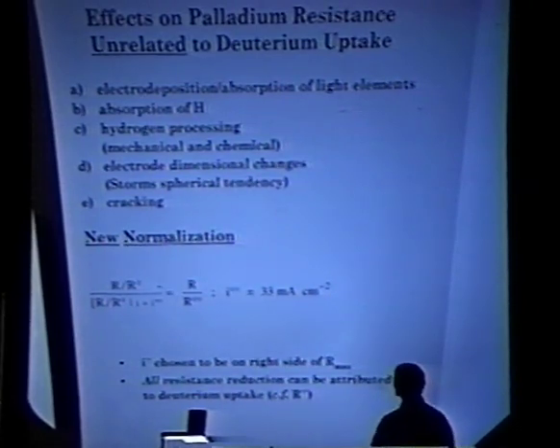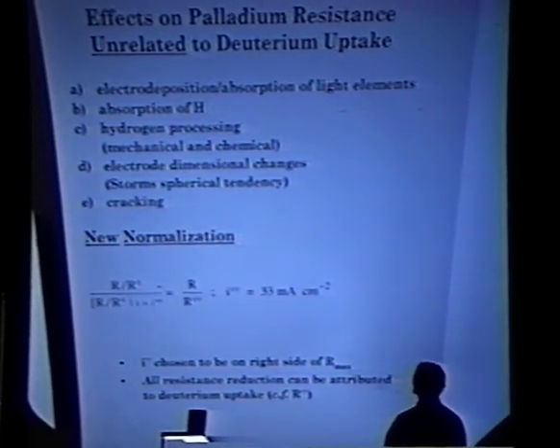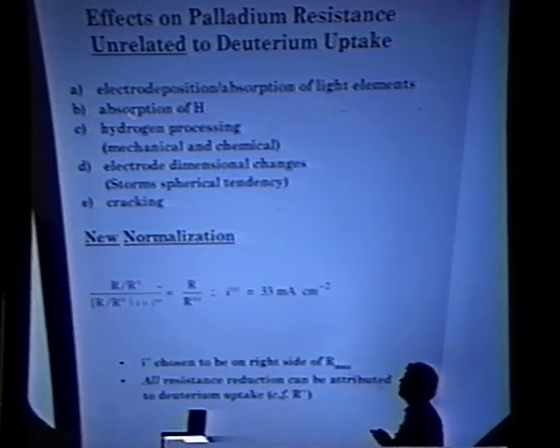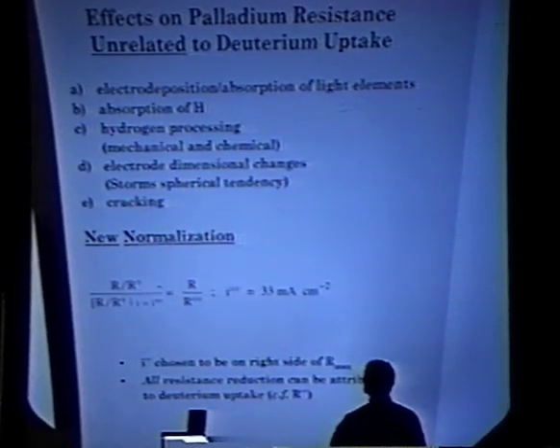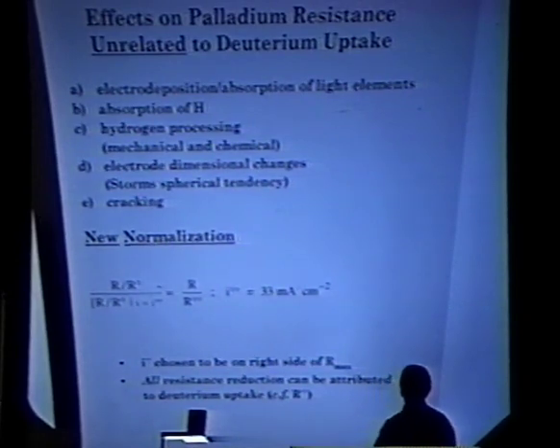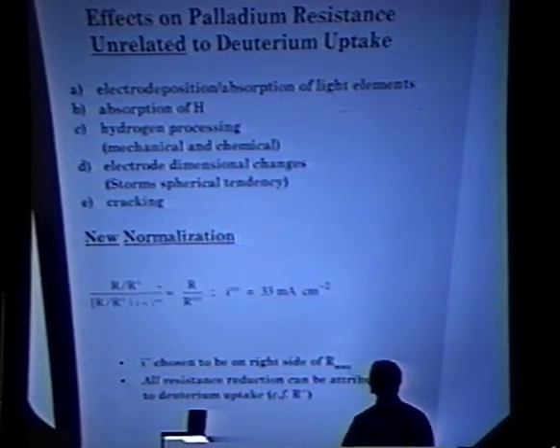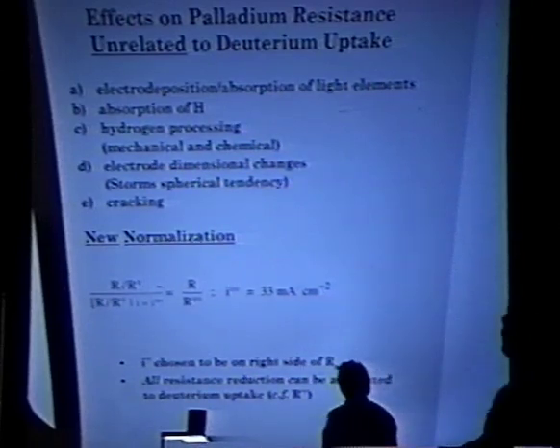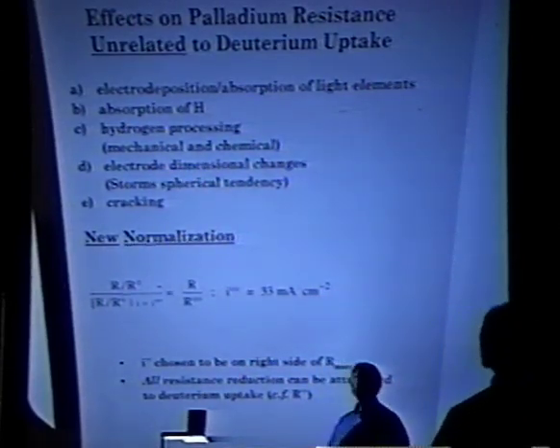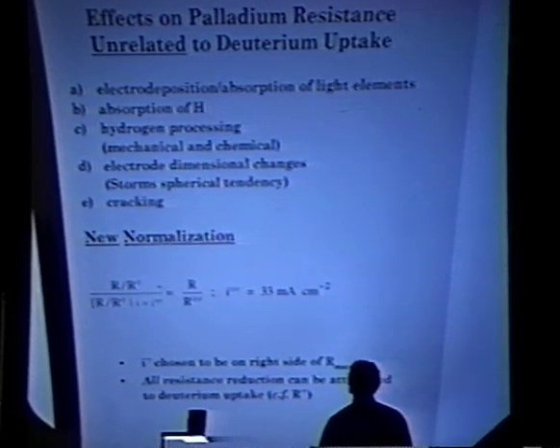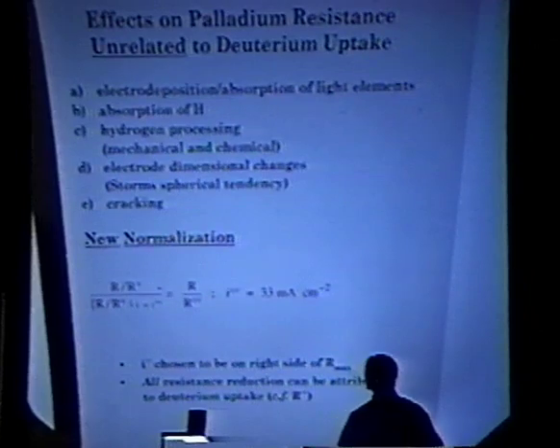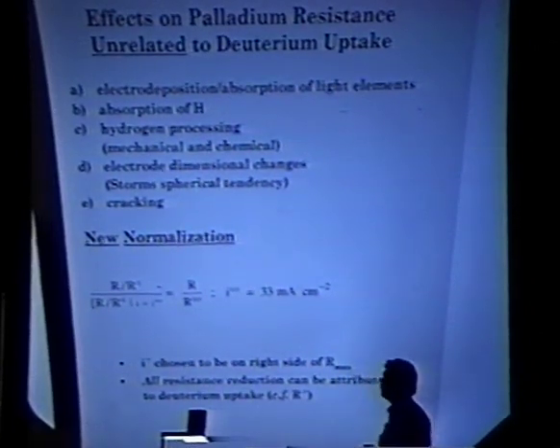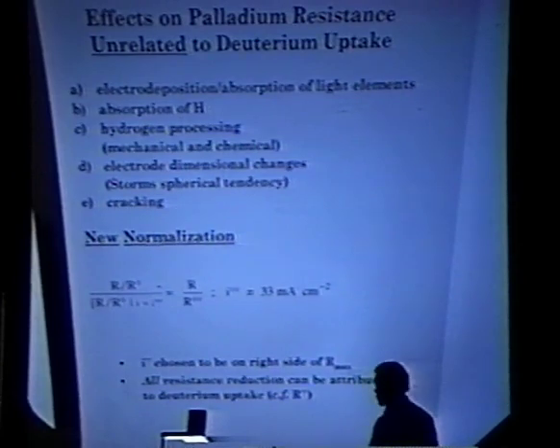Electrodeposition and absorption of light elements, boron, beryllium, carbon, all affect the resistance. The absorption of protons, which happen to be in the electrolyte, changes the resistance ratio without changing the D to PD ratio necessarily. Also mechanical changes introduced into the electrode by the cold work associated with the absorption of deuterium into the palladium lattice. Electrode gross dimensional changes, which Ed Storms pointed out, the tendency towards a sphere, cathodes becoming more spherical in shape as they are exercised and cycled, and cracking.